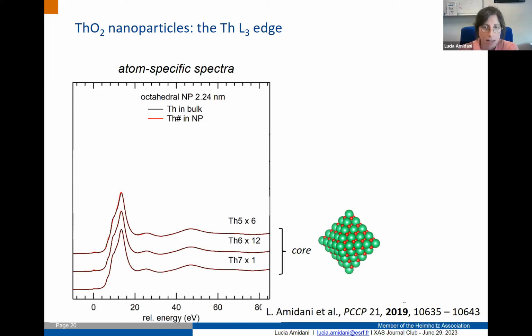Here, as an example, what we get is a simulation using the same sort of framework that I showed you to simulate the bulk, but just changing the structural input. If we stay in core atoms, atoms that are inside the nanoparticles, as you see, they superimpose with the bulk. The bulk spectrum is in black.